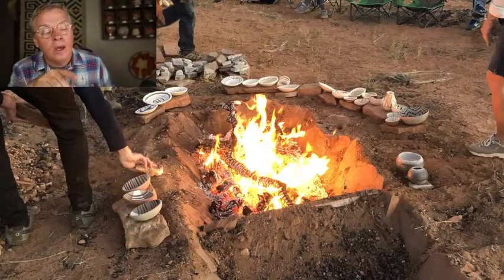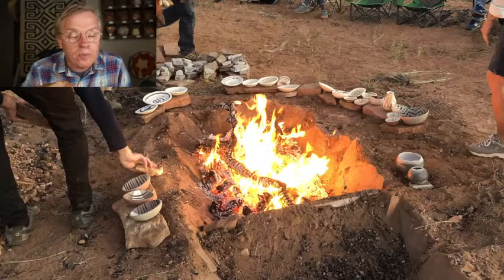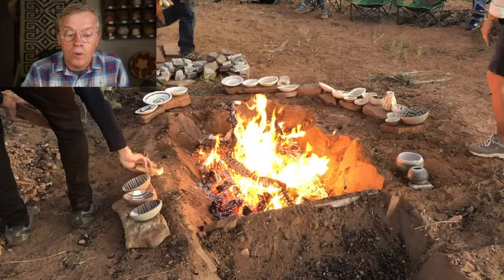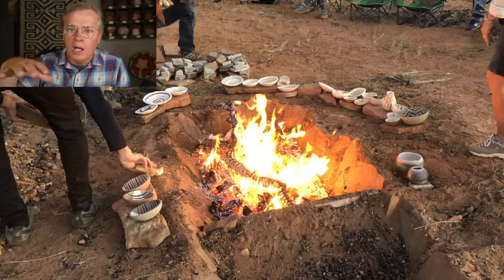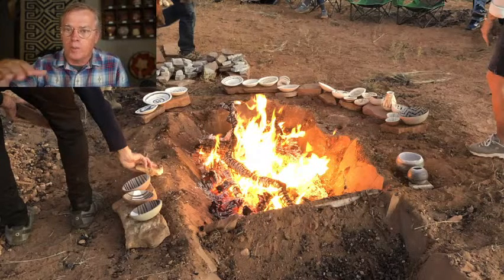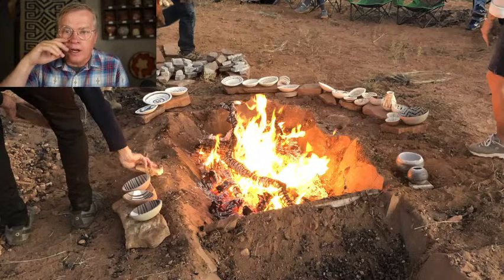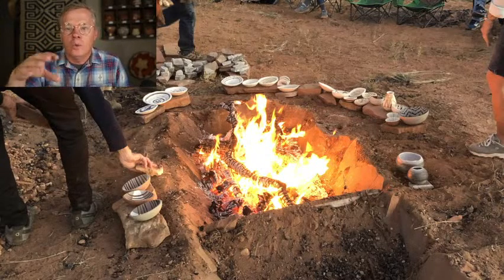And there's a contingent of people, not just Owen, but a few that think that these ancient trench kilns perhaps were not smothered, that they were fired in some other manner than the way they're being fired today. So at the 2021 Southwest Kiln Conference in Blanding, they did an experimental firing, and this is it here. In this firing they said, we're not going to smother it. We're going to allow a layer of ash to form on the top, and we think that ash will keep out enough oxygen that we should get the same results without smothering it.